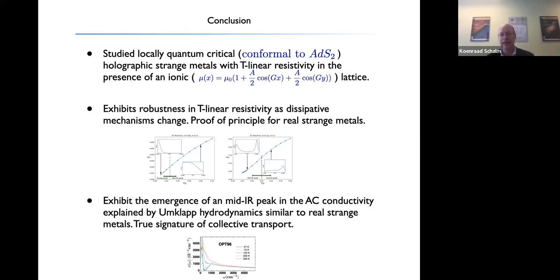Thanks to this Umklapp hydrodynamics, there are various components or various combinations of thermodynamic quantities that contribute to the dissipation rate. And it could have been that as you change the temperature, one dissipative mechanism takes over from another dissipative mechanism. But that doesn't happen. And the reason that doesn't happen is because, secretly, due to the underlying criticality of the Gubser-Rocha fixed point, these all scale in the same way. And this way you can explain the emergence of a mid-IR peak in the AC conductivity, which is naively a change of underlying dynamics, even though the linear in T resistivity stays the same.